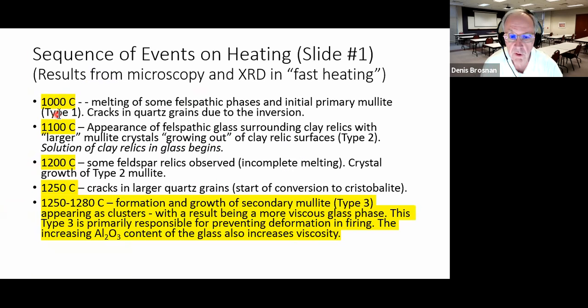At about 1,000 degrees, we begin to get some melting, and a little bit above that temperature, we can begin to see some shrinkage in the product in firing. At 1,100 degrees C, we have the formation of a feldspathic glass. In some products, you may have a ramp in the firing schedule up to about 1,100. You may slow down at 1,100 and heat more slowly to try to enhance the development of this glass phase.